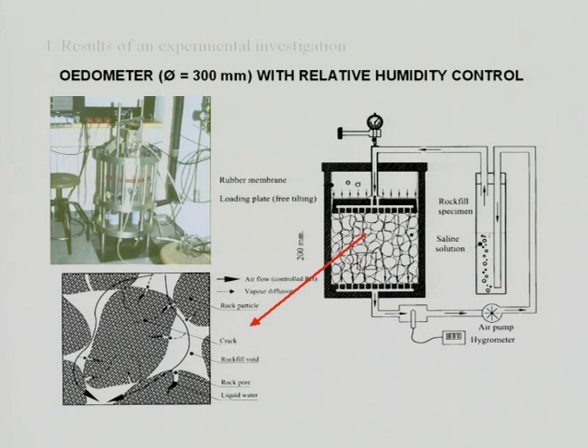And this is the cell that we built. This is the first cell. This is an oedometer cell for samples up to 30 centimeters in diameter with relative humidity control. The most important feature of this cell is that we can circulate air with a given vapor pressure. And the vapor pressure is controlled here in a saline solution. So you circulate this air with a vapor pressure, and eventually, after some time, some equilibration will be reached within the sample.